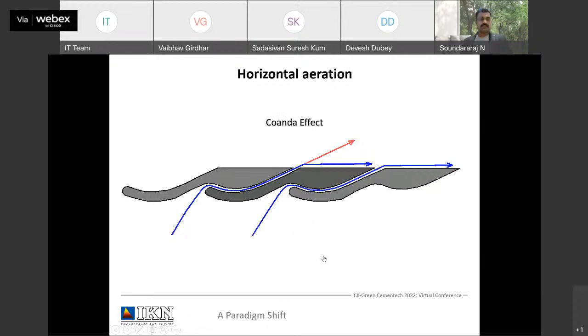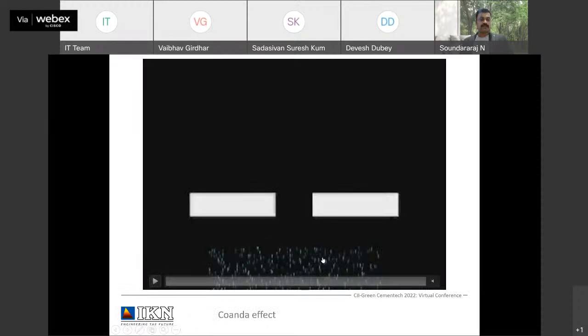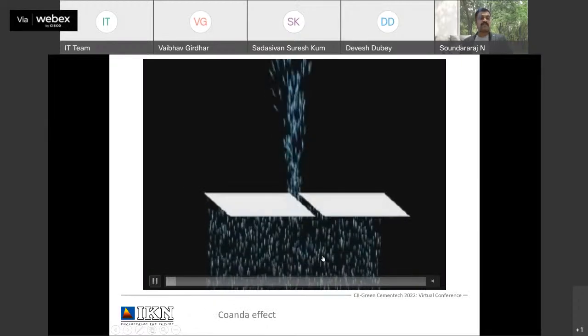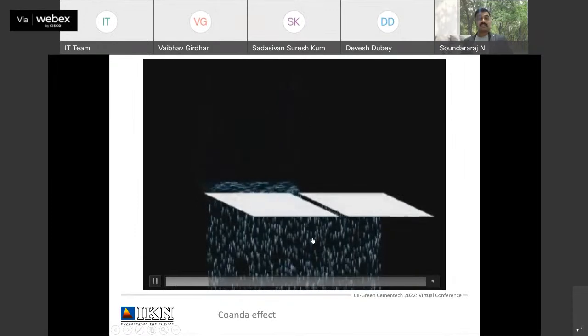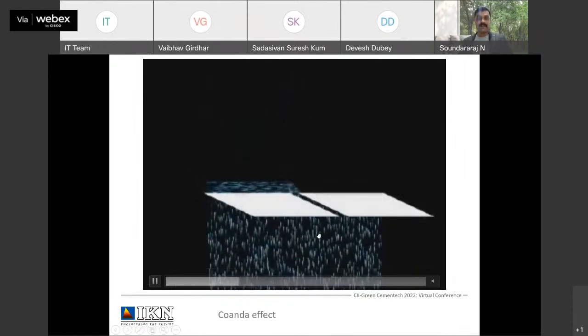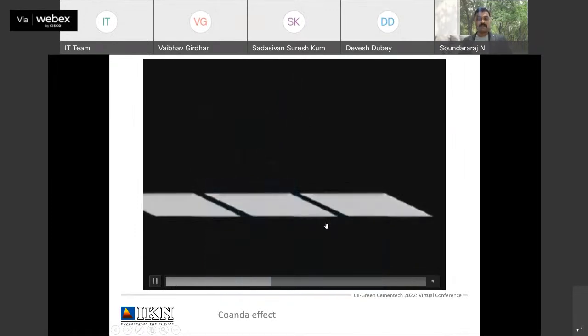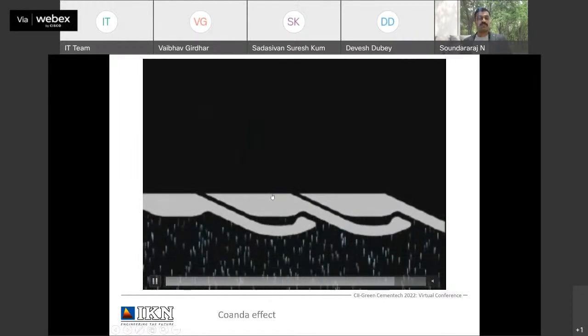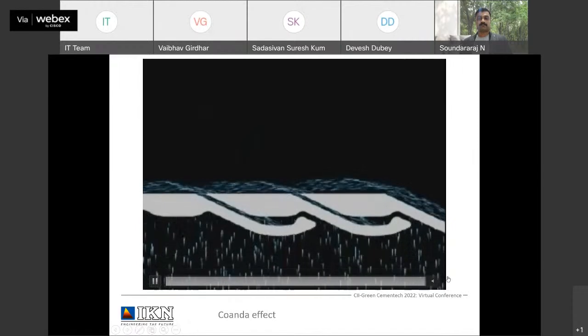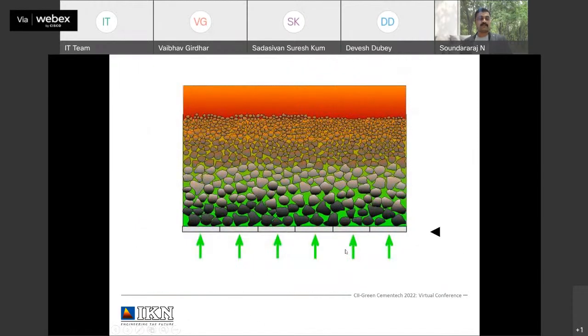In this video, you can see in this grate technology, the air passes parallel to the grate surface and it simulates 10,000 holes. You cannot drill 10,000 holes, but by passing air parallel to the grate surface, you will be able to simulate 10,000 holes. The cooling air reaches every clinker particle and thus exchanges the heat to the maximum possible effect. This is called Coanda effect.